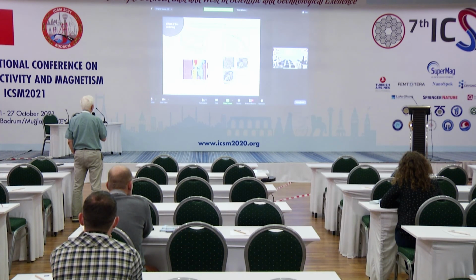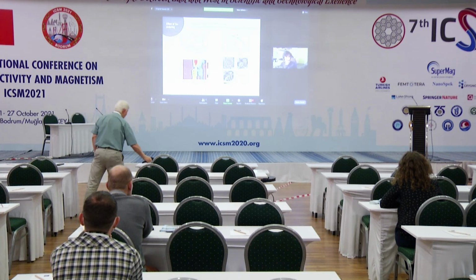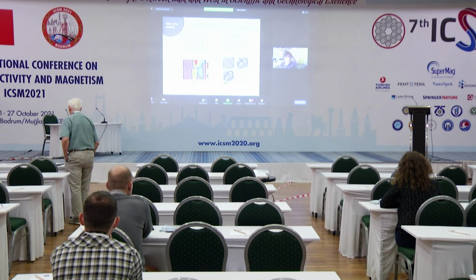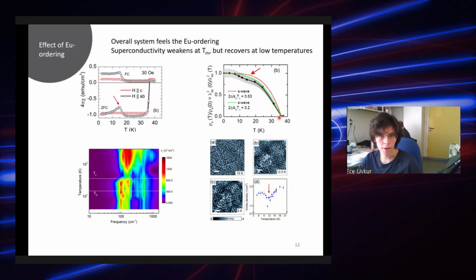Did you try this? Okay, so you're absolutely right. First of all, when we actually did this work, the ARPES measurements hadn't been done yet, so we didn't know the superconducting gap values for this sample at all. So this optical spectrum was the first one to give some sort of a gap value. We tried to fit this with two s-wave gaps. It is possible, but technically then the other gap is even smaller than 5 millielectronvolt. It is possible, but that shouldn't be really that visible in the optical spectra, because this is out of our range. I mean, I should be able to see what is already observed plus something larger.